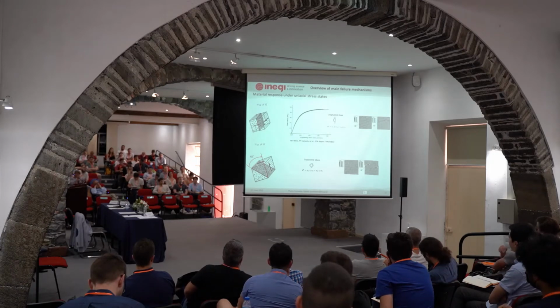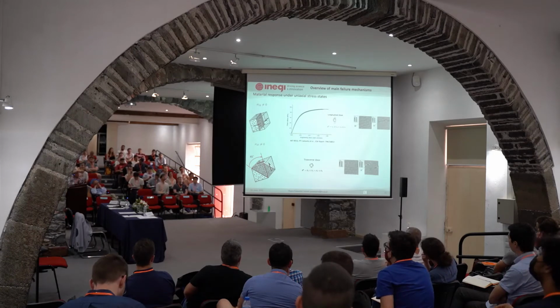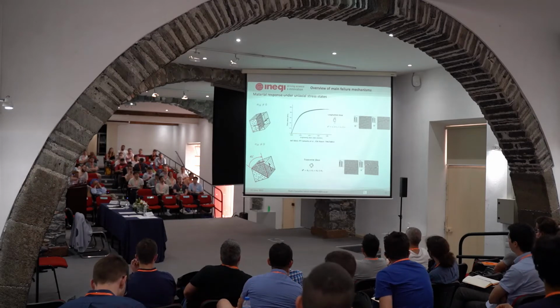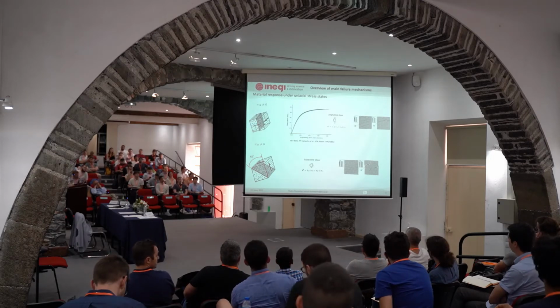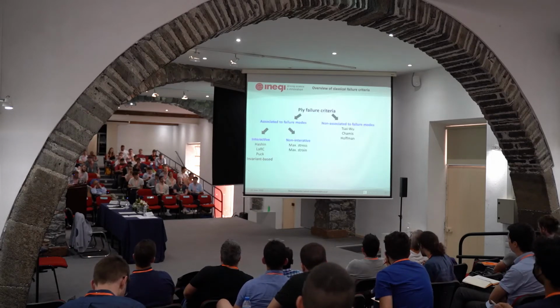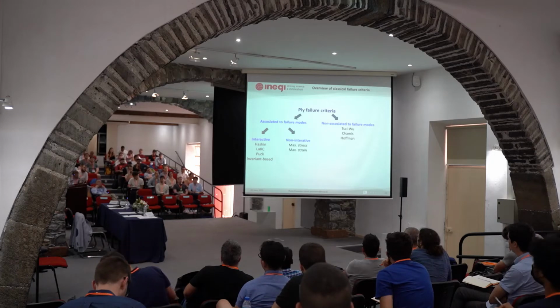You get typically a fracture angle of 45 degrees, which means that it's the maximum principal stress that is creating this crack in this crack plane, so perpendicular to the maximum principal stress. Okay, so this is how the material responds under uniaxial stresses. And now we need to simulate, we need to predict these failure mechanisms, okay?